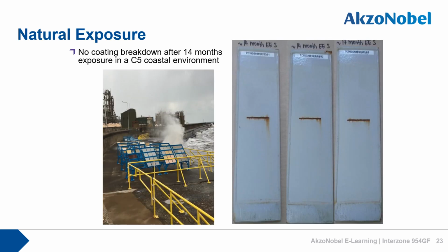A key part of the technical confidence that we build in products is to correlate the accelerated corrosion testing to natural weathering exposure in climates that mimic real-world exposures. In this slide, we can see a coastal exposure site that we own in the northeast of the UK, which is representative of a typical C5 or coastal atmosphere. As you can see from the photos of the panels on the right, there was no corrosion on the panels that have been exposed for 14 months at this coastal exposure site. And these panels had a scribe in them, which is meant to mimic damage in transportation and handling that we typically see in new construction projects.